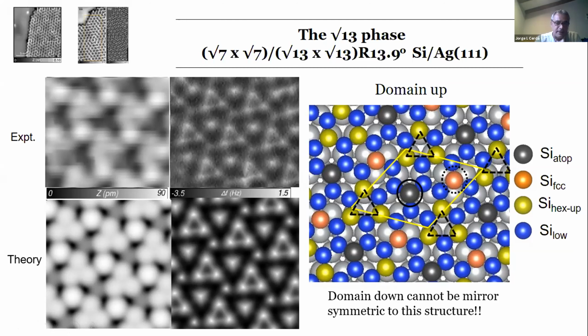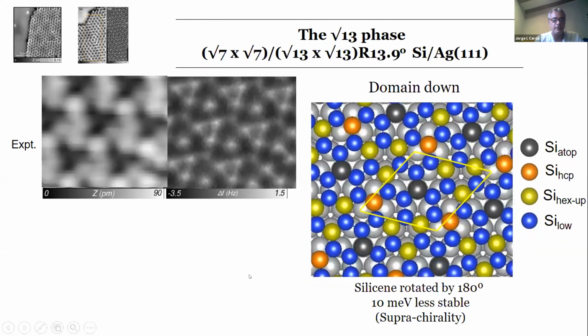What we obtained here is a system where we have the triangles pointing up. What about the structure with the triangles down? Well, again, we cannot obtain it by mirror symmetry. So we did the same trick as before. Just rotate the whole silicon layer, maintaining the silver intact. And this is a structure we get, which is, again, basically with the same stability as the previous one.